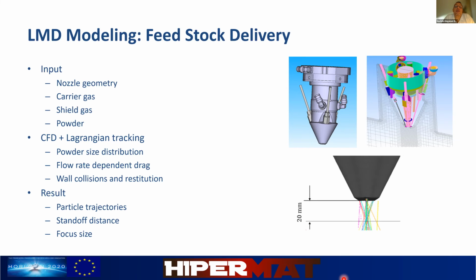As you see, because of the collisions of the particles with the walls, and also because of crossflow, some of the particles move sidewards or don't even move towards the focal point. Those particles are usually lost to the process. And if you count these particles, you can actually calculate an efficiency of powder capture. That is usually around 60%, which we did not quantify for this particular case here. The next slide, please.